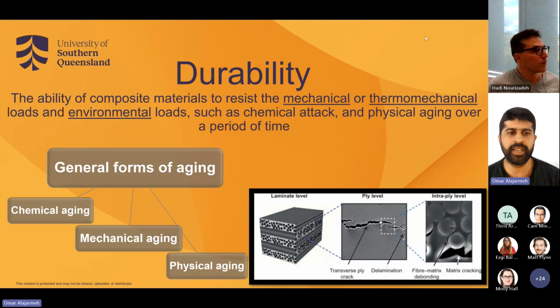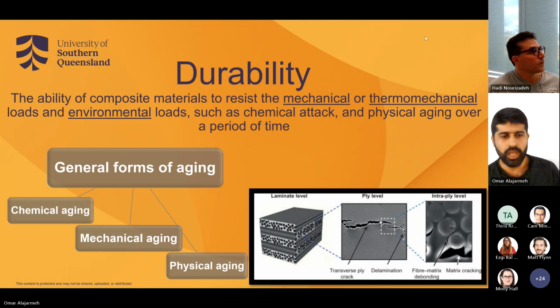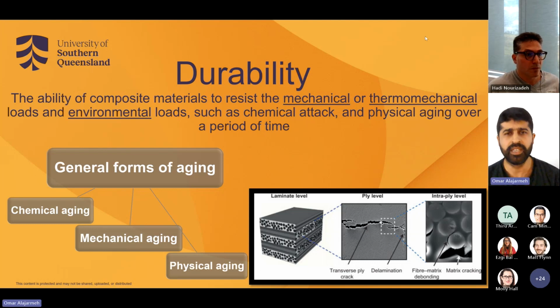Okay, it's good to understand what the conditions are that can affect the service life of the composite. I listed the general forms of aging for composites: chemical aging, mechanical aging, and physical aging. It's not a sudden impact on the composite, but a time-based impact. If you look at the figure here, you will see how it goes in depth from the laminate level to the ply level, having small micro cracks, localized debonding between the fibers and the matrix, micro cracks in the matrix, and even changing the behavior, or the chemical form, of the matrix.